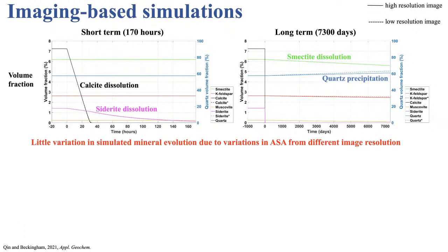So this is the results from the imaging-based simulations. What we see over short time scales is we have rapid initial calcite dissolution. We also have siderite dissolution. Simulations that use the surface areas from the high resolution images are the solid lines, and the dotted lines are using the surface areas from the low resolution images. And you can see here over this short time scale, there's really little difference in the simulation results.